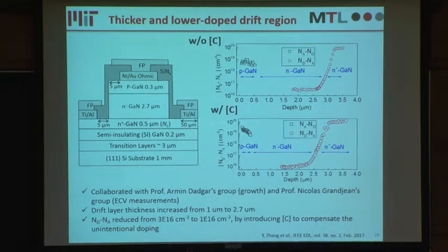We also use some carbon to compensate the unintentional doping in this region. Here is the profile of the acceptor and donor concentrations in this GaN-on-silicon wafer. Without carbon compensation, the donor concentration in this drift region is 3 times 10 to the 16. After carbon compensation, it can be reduced to 1 times 10 to the 16.